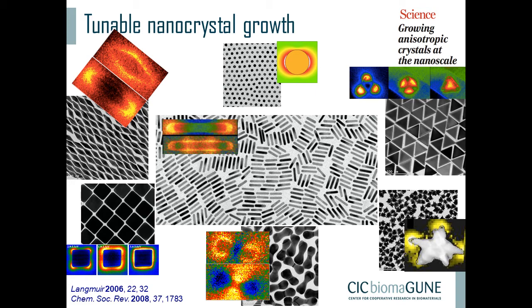So these pictures that you see here are so colorful, except for this one, they are actually all experimental data that are measured with an electron microscope by doing electron energy loss spectroscopy. And these bright spots that you see at different parts of the particles are equivalent to the enhancement of the electric field that we would obtain by illuminating with light. And so now we can really do also single particle or even multiple particle analysis of the optical morphology to enhance electric fields if we want to do applications in that respect.